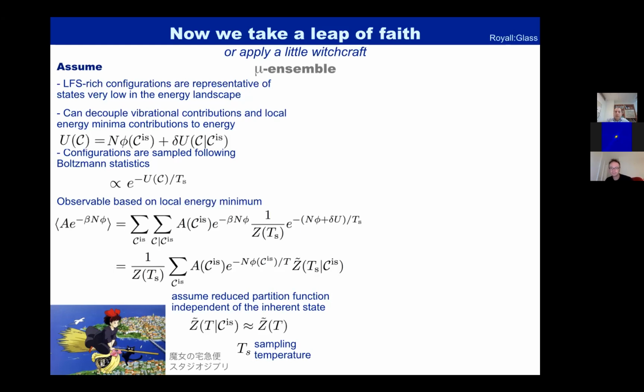Okay. So nowadays there is this other approach that is becoming extremely popular to go close to the Kauzmann temperature, which is the swap algorithm. I guess the swap algorithm will go to crystallization in your model if it is a monodisperse system. It's not. Oh, I'm sorry. This is the Kob-Andersen binary Lennard-Jones model, but swap is inefficient for that because swap works better with a more continuous distribution of particle size.